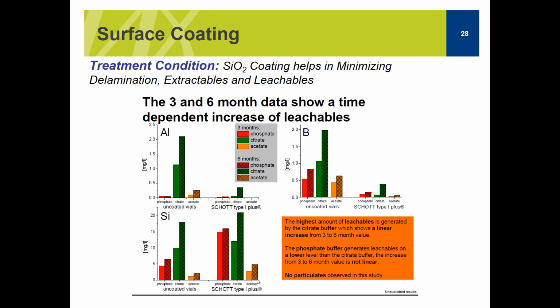Okay. Now the other thing that you can get from these graphs is the fact that the longer you store your product, the higher the probability of delamination that occurs, and the more extractables and leachables you will see. Okay, and that is very common here in all of them. So citrate buffer here for the uncoated, at 3 months we had 10 milligrams per liter of silicon, but in 6 months that almost doubled, so it went to over like 19 or so. Okay, so this is saying that SiO2 coating helps, but still has limitations.